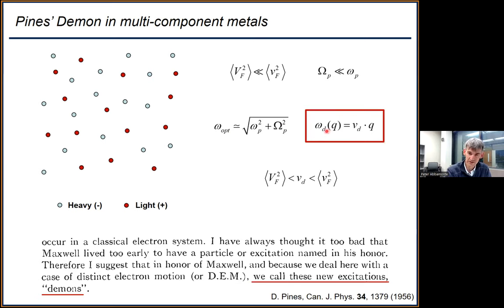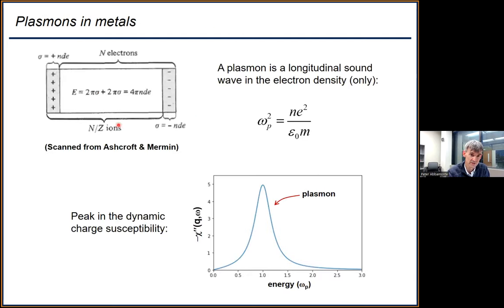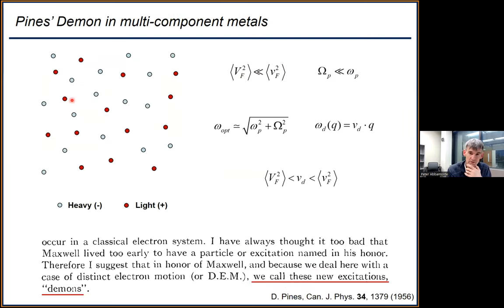Now, what does gapless mean? Gapless means that this thing isn't sitting up at some high frequency. Its frequency is actually proportional to its momentum, the proportionality constant being some kind of velocity. And that velocity would be similar to the Fermi velocity of the electrons in the two bands. And this is a very strange prediction. It's very hard to make a plasmon-like excitation that's gapless. And the reason, if you come back to this basic plasmon argument, is if I try to move charge, it always costs this Coulomb energy. This is why plasmons sit at high frequency in metals. So it's a very odd thing to make a prediction that there would be a plasmon-like excitation that is...